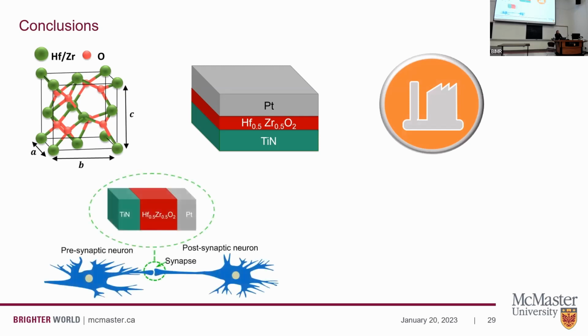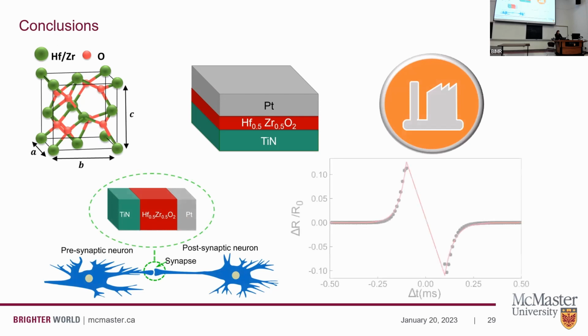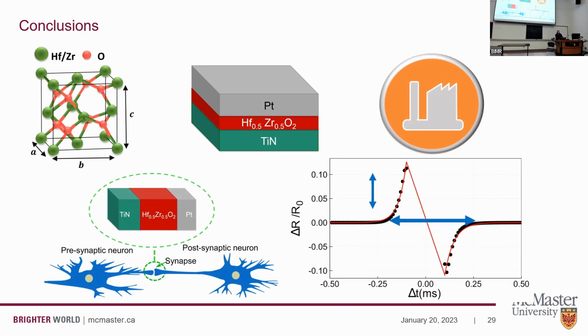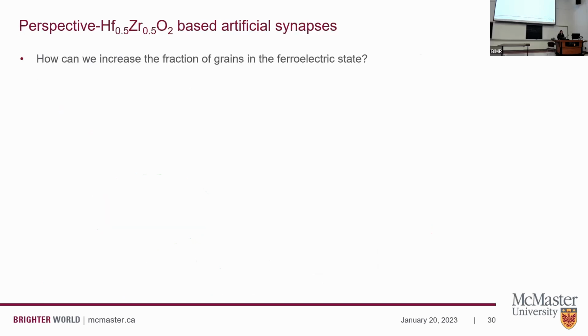We then went further and looked at their potential for artificial synapses that have the ability to learn just like the human brain. And by looking at spike-timing-dependent plasticity measurements, we were able to confirm that those devices had indeed the potential of mimicking the behavior of synapses. However, the resistance change remains fairly low, while the response time also remains very slow compared to that of our brain. And this could be further improved by improving the quality of the material, which will be done by probing into the material structure and trying to understand it a little bit more in order to control it and to tune it to specific applications.